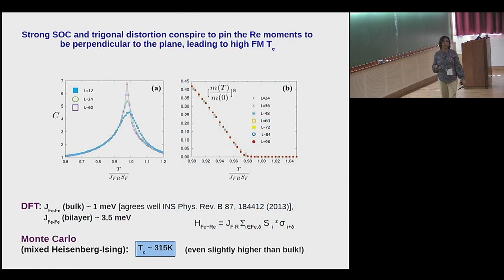And what about the high temperature? I started with the motivation that this will be a high temperature system. The strong spin-orbit coupling and the trigonal distortion conspire to pin the rhenium moments out of the plane, making them completely Ising-like. So if you do a Monte Carlo study of a mixed Heisenberg-Ising model, because the iron spin still remains Heisenberg while the rhenium spin behaves like Ising, you compute the Tc, and because the large trigonal distortion and the strong spin-orbit coupling make it behave almost Ising-like, you get that the Tc is even slightly higher than the bulk.